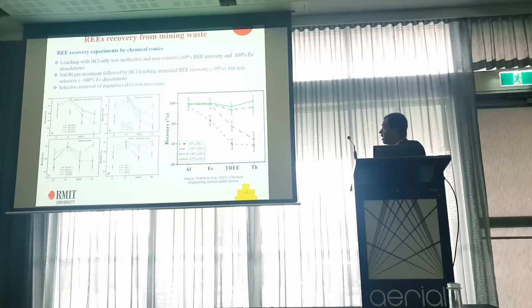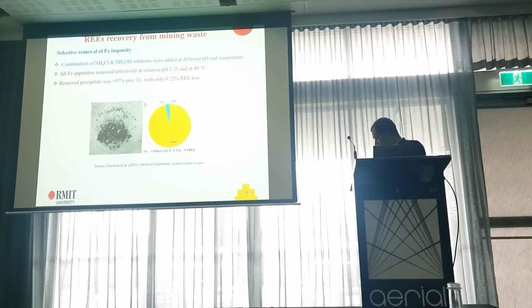hydrochloric acid, and here the rare earth recovery increased. Again, iron was a problem, so selective removal of impurities, particularly iron, was necessary. Then we worked on how to separate iron from the rare earth recovery. In the treated sample, we have only rare earth separated from the iron. The next work was pH control and temperature control.